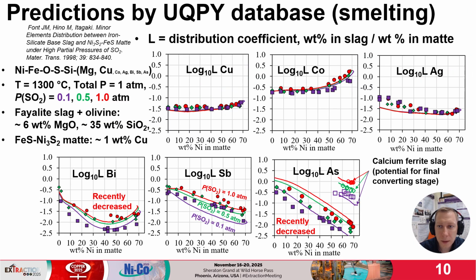In the follow-up study, the distribution coefficients for impurities were also measured. They can be modeled. The distribution coefficient is the ratio of concentrations in slag versus matte. They are typically presented in logarithmic scale because they vary so much. Overall, the model is believed to describe the distribution coefficients for copper, cobalt, silver, and bismuth within the accuracy of experiment. For antimony, there is some underestimation, and for arsenic, overestimation. For arsenic, it was recently remodeled to lower values, but the model is still a bit higher.